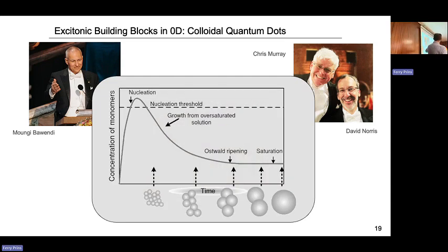The key here is that you are basically controlling the concentration of monomers. The moment that you inject, you need to get very, very fast above the nucleation threshold. Once you nucleate, there's going to be growth from the precursors that have not yet nucleated. So you nucleate, you start growing immediately, and that of course decreases the concentration of monomers. So in a one-pot synthesis, you are controlling both the kinetics and the thermodynamics of the system, the growth of your quantum dots.